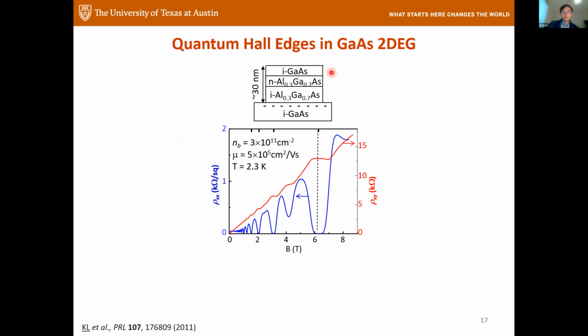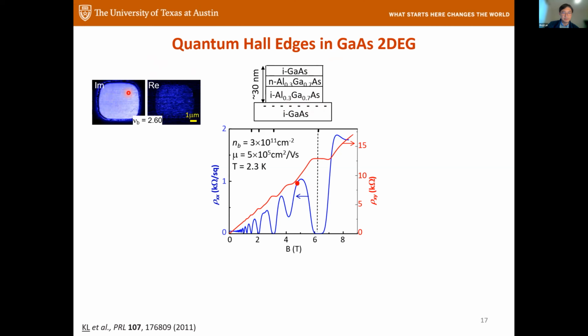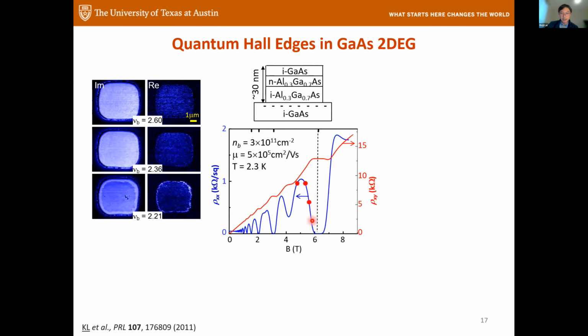And so we measure different dots at different magnetic fields, because unfortunately, if we don't do that, this very shallow 2DEG is getting depleted. You're going to see a lot of these images, but they're taken from many dots, and these are from different ones. So we start from here, very far away from the quantum Hall dip, and then we gradually enter this dip.